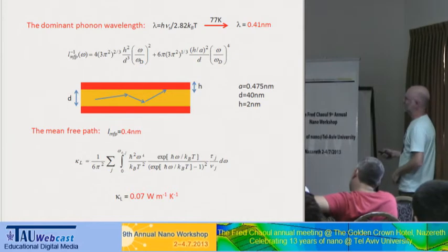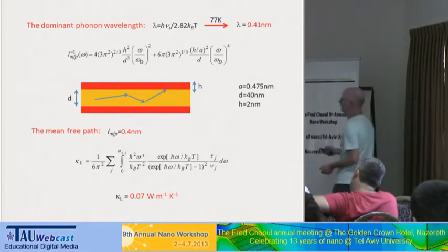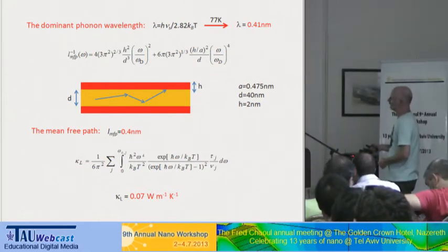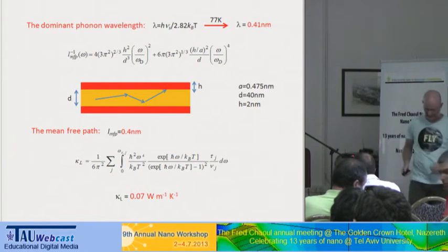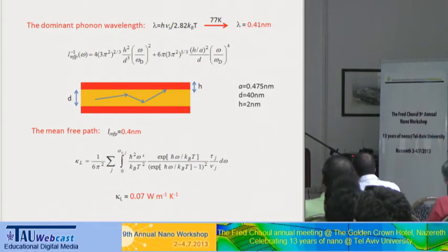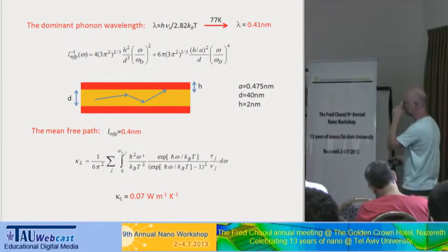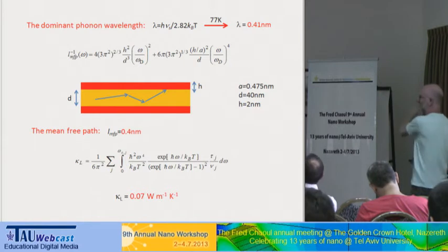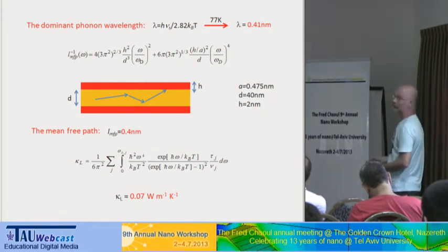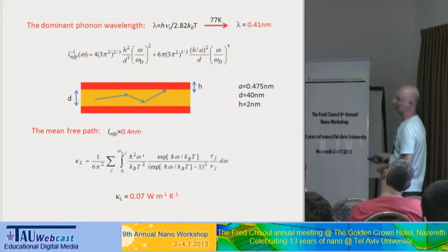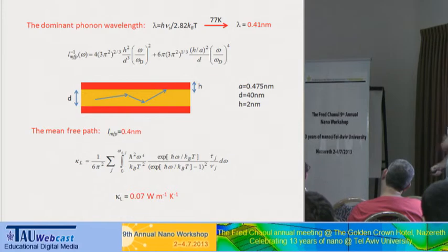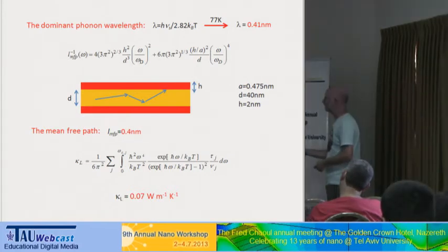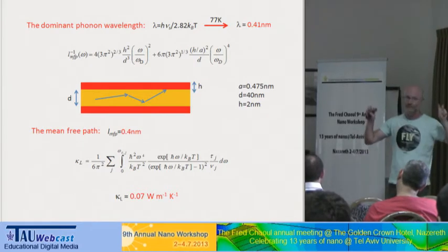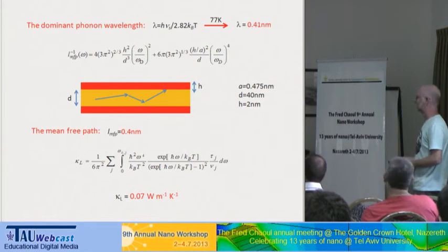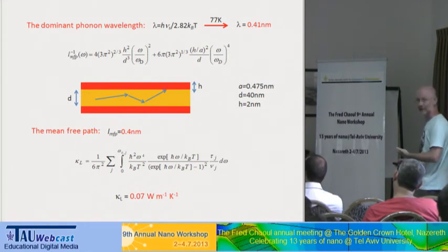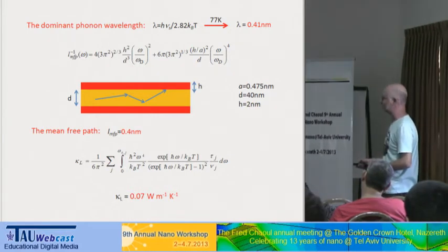Based on this equation here, which I won't go into the details of how it is extracted, it calculates the mean free path of what is called, skip the terminology, the mean free path of phonons that are going here with vanishing wave vector, which is perpendicular to the main axis of the wire. And the mean free path here is 0.4 nanometers, which is exactly the dominant phonon wavelength of the Bismuth. What it means is that if you have a mean free path which is exactly this, you have an amorphous material. And if you have an amorphous material, you can put all the values inside and calculate theoretically what you would expect to see for the thermal conductivity, and it's 0.07.